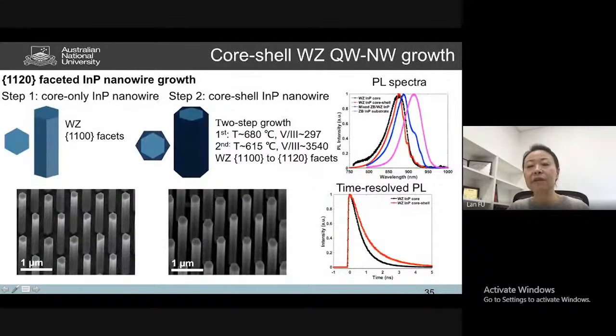So we're not really satisfied with just that, because as I mentioned, we grow nanowires based on the Wurtzite-zinc blende mixed phase, which enables us to achieve very uniform quantum well growth. But one of the issues with that growth is that the recipe, which from the beginning starts from very low temperature and high V/III ratio, actually promotes a lot of lateral growth. So basically, it enables the nanowire to grow in the radial direction rather than the axial, length direction.